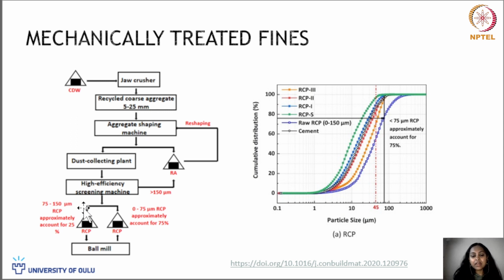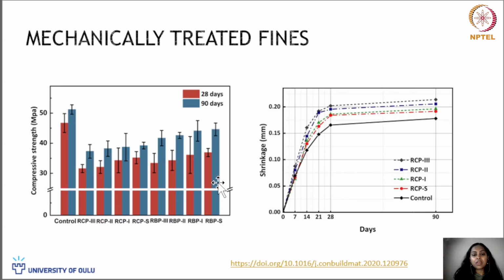So here you see that you have this recycled concrete powder, which is again milled using a ball mill, and it is said that the reactivity is improving by reducing the size of this material, which is expected to be because of destructing the crystalline structure of the hydrated products from the old cement. However, when this is replaced with the Portland cement in these mixes, there is a decrease in the compressive strength. So still it is not equivalent in performance compared to the actual cement that we are using in recent days.